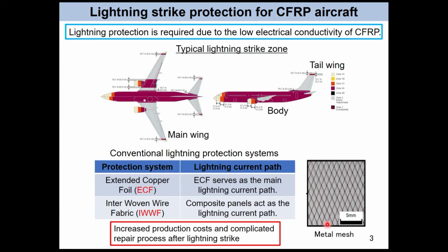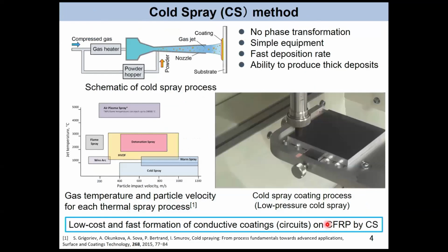This is a problem. So one attractive method is the cold spray method. I show the schematic of the cold spray process here. Particles, normally 10 to 50 micron in size, are put into the gas, and the particles are accelerated by the gas and impact on the substrate to form a coating.